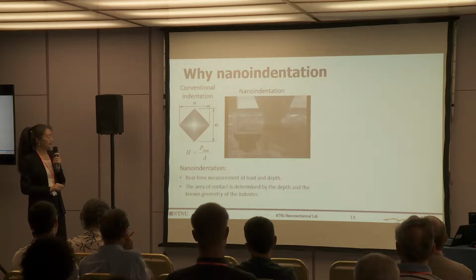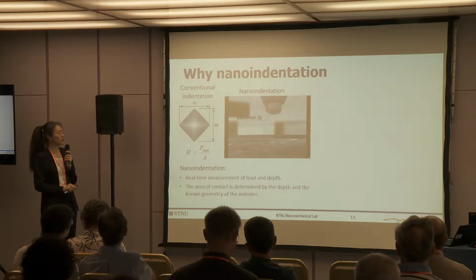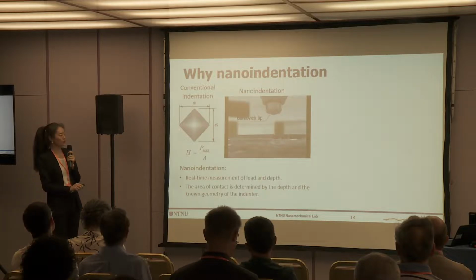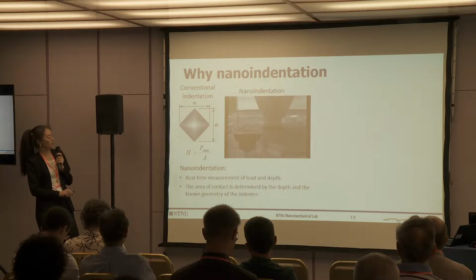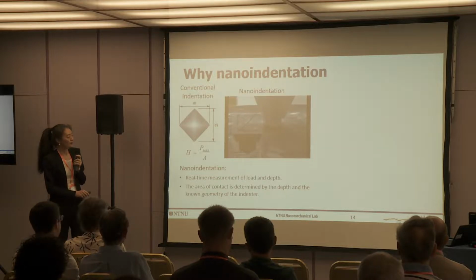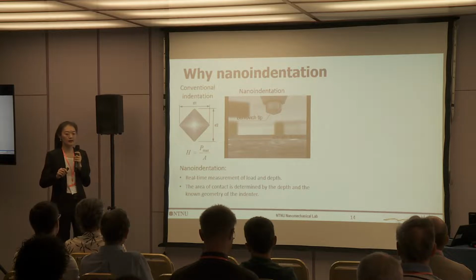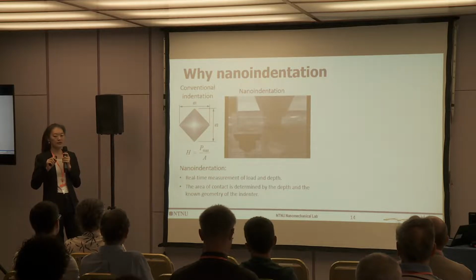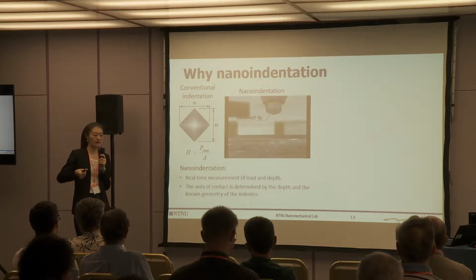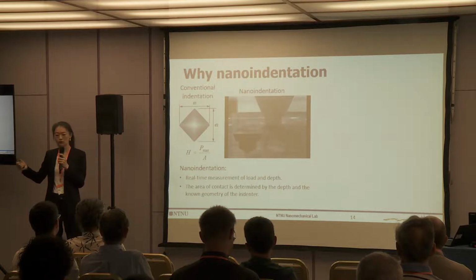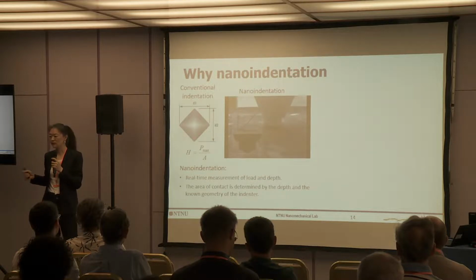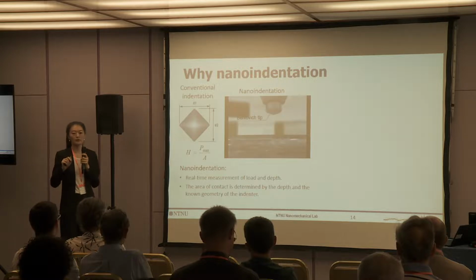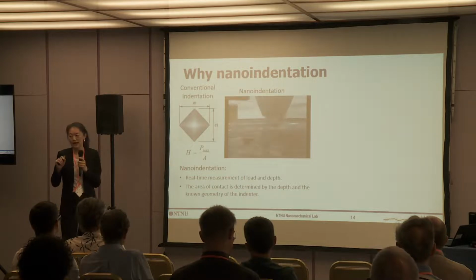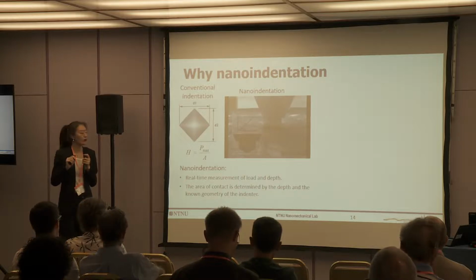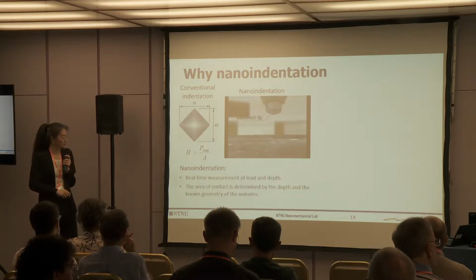Comparing with conventional indentation, we make an indent with a predefined load, use an optical microscope to measure the diagonal length of the residual indent, then we calculate the material hardness. Nanoindentation uses a much smaller load, and at the same time, we monitor displacement. Then we plot the real-time force and displacement curve. Think about it, if you punch a hard object into wood or stone or steel, they all respond differently. So this load and displacement curve is the fingerprint of the mechanical response of your material. Based on that, you can analyze many different mechanical parameters of the material.